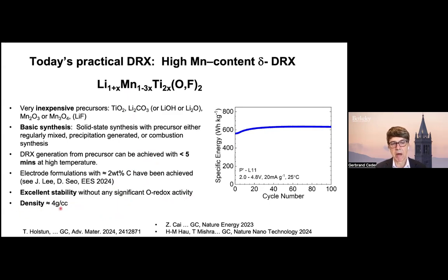A good number to keep in mind is the crystal density is about 4 grams per cc. So that's lower than NMC and higher than lithium iron phosphate. And again, a lot of the research work has a very high amount of carbon in the electrodes, because particles used to be heavily milled. Today, there's some really fascinating work done by Donghwa Seo at KAIST in Korea, together with Jin-Yuk Lee, who's one of the co-inventors of DRX, who's at McGill, showing electrodes with very low amounts of carbon.